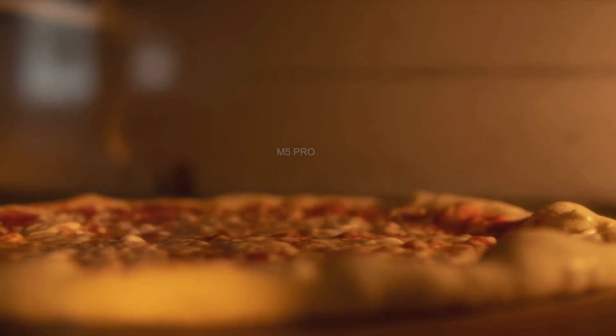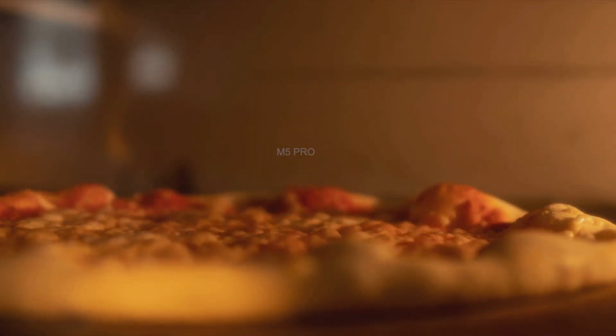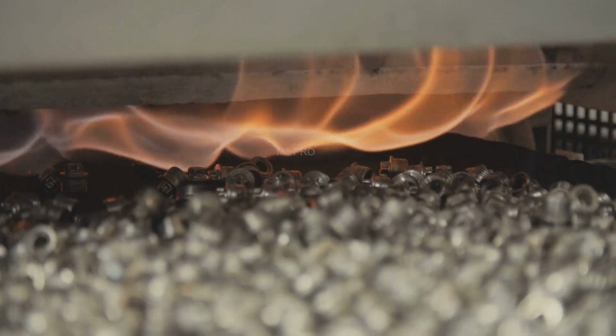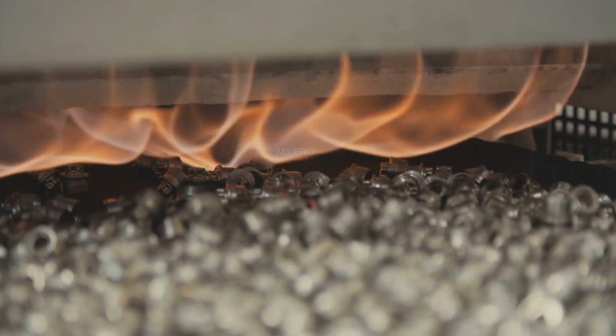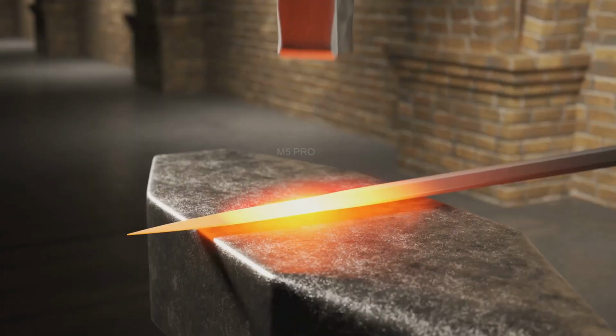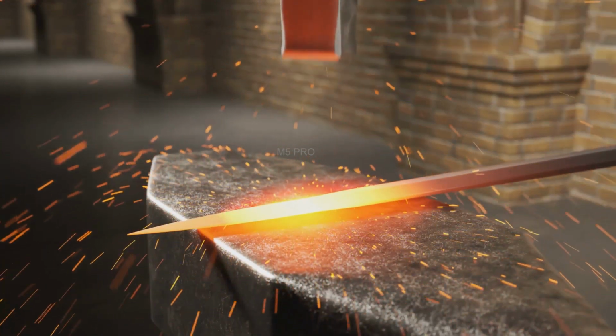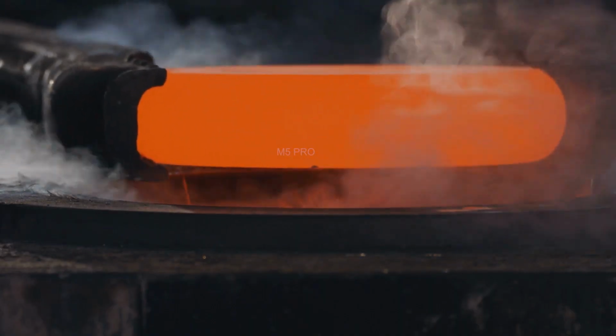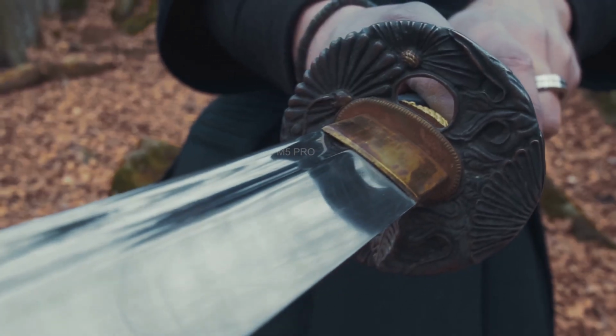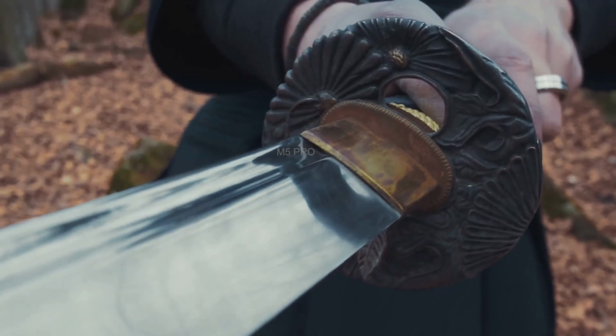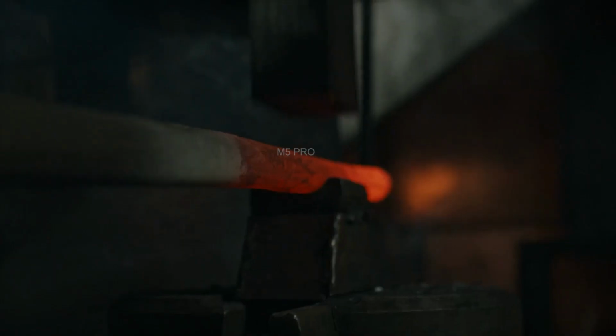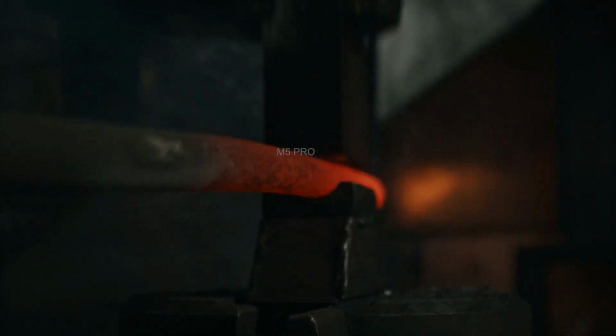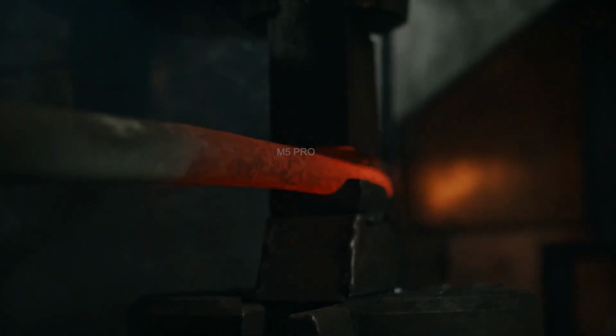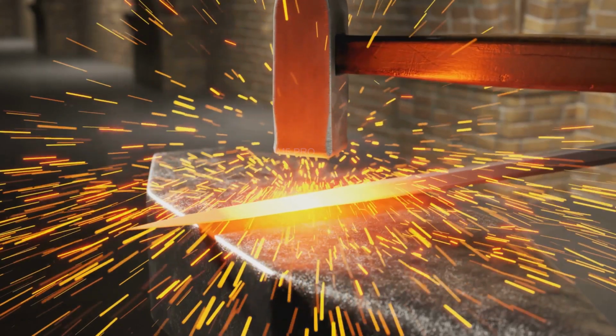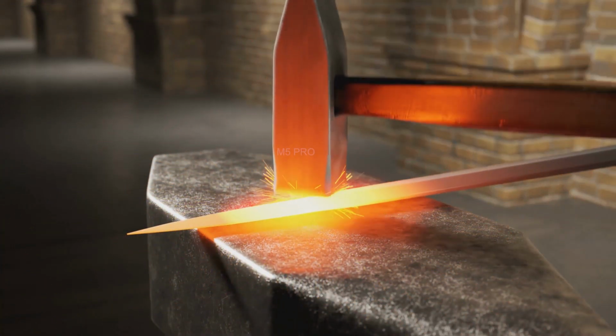The blades sit in the oven for a set period, usually a few hours, allowing trapped carbon atoms to precipitate out of the martensite. That transforms brittle, needle-like martensite into a refined, tougher structure. You can actually see the effect on the steel's surface. As it heats, it forms a thin oxide layer and changes color. Light straw yellow, darker bronze, purple, and finally blue. Those colors indicate temperature, and by extension, the steel's final properties. For a cleaver, we often aim for darker straw, or light bronze.